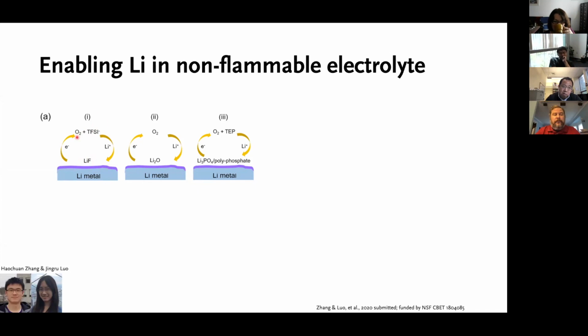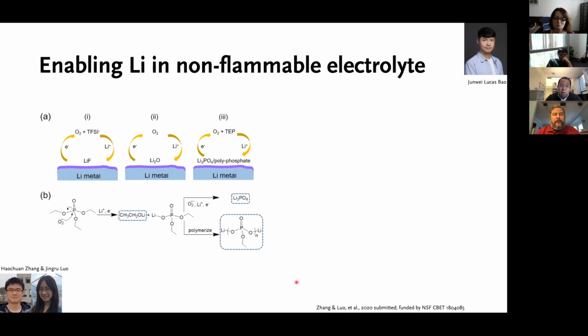Their control experiment proved this route is unlikely. An alternative reaction could be that the oxygen is just reduced by lithium to form lithium oxide. Lithium oxide has also been tested as a component for SEI. Their study also proved this is unlikely. So this left the most likely process to be oxygen-induced or electrochemically induced decomposition of TEP. With the help of our new colleague, Lucas Rao here at BC, whose expertise is in DFT calculation and computational chemistry, Hao Chuan and Jin Ru proposed this reaction mechanism that involves the superoxide radical attacking the phosphorus, releasing ethoxy oxide and lithium oxide, and then eventually leading to a chain reaction that forms lithium phosphate or polymeric lithium phosphate.